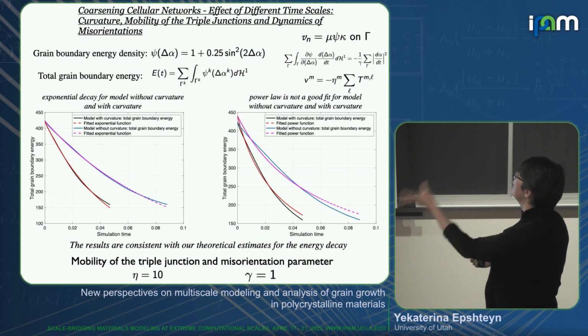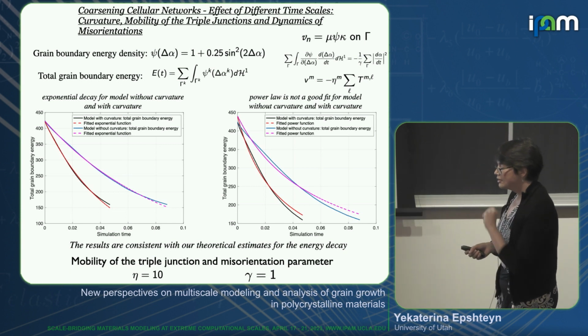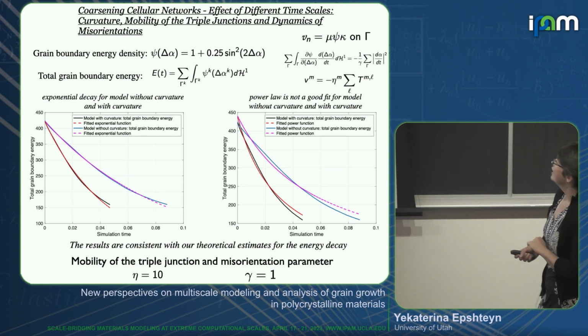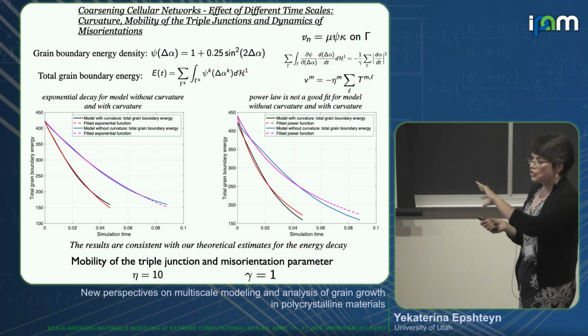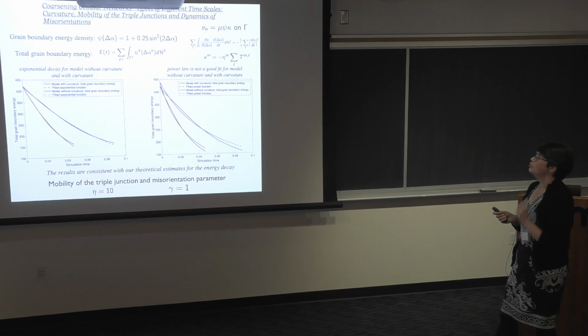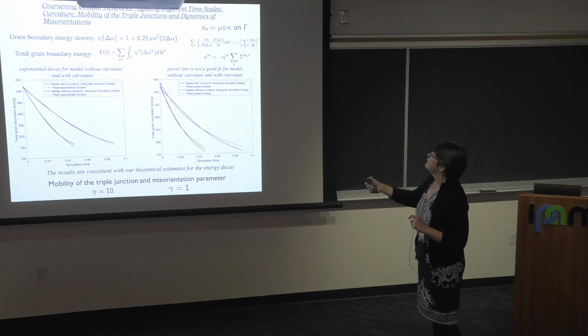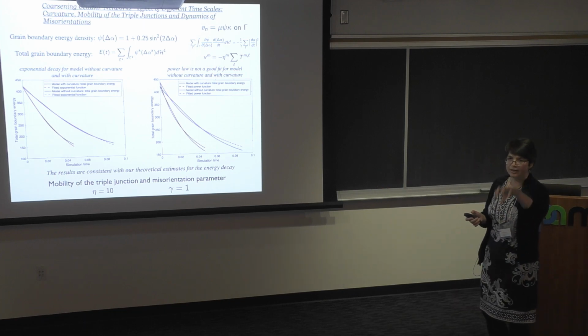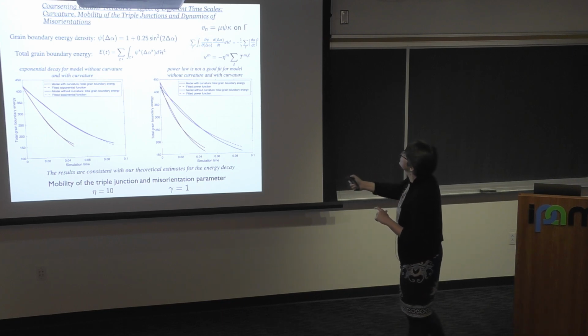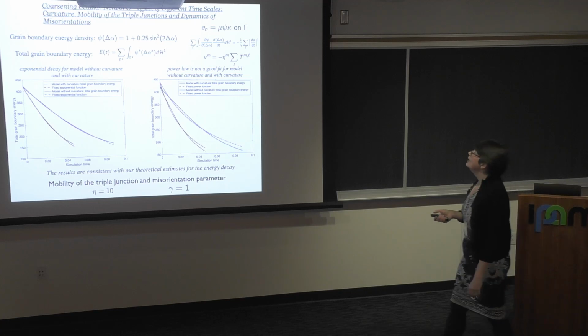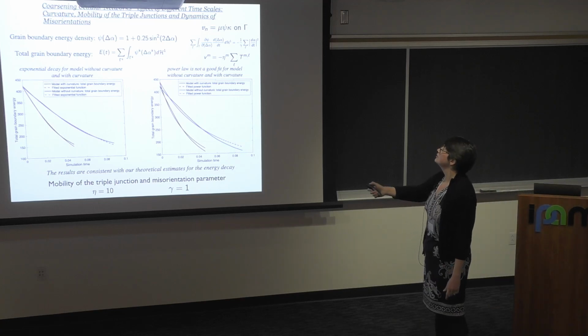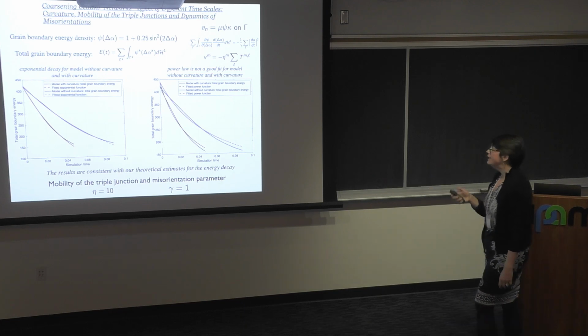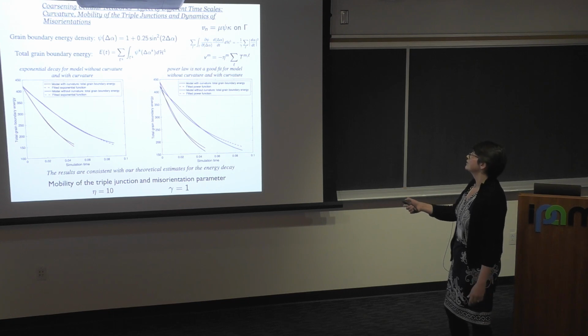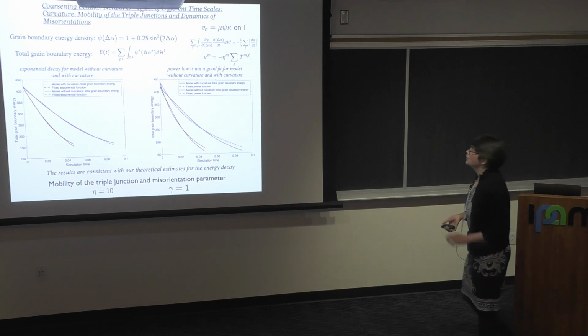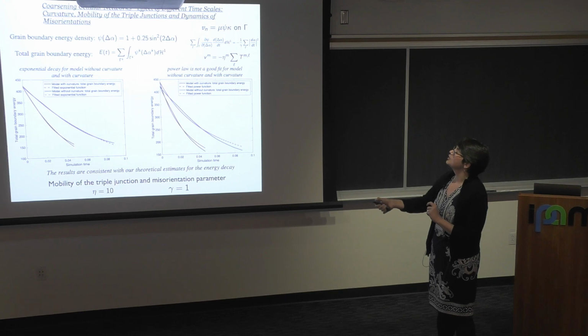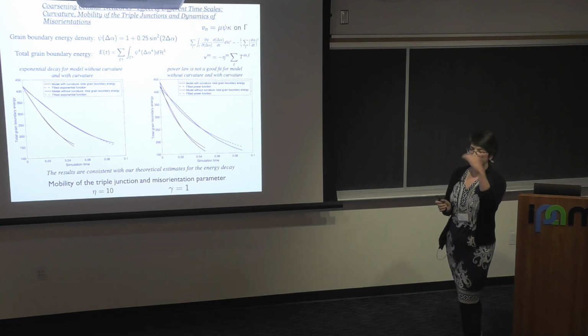Okay, but what I want to show, so I discussed that we have a reduced model where we relax dynamics of grain boundaries. We have a full model. So what we did numerically, we wanted to compare in some aspects the reduced model and the full model. Numerically, I will consider the full model that takes into account dynamics of grain boundaries, dynamics of orientations, and dynamics of triple junctions. And I will compare it with a reduced vertex model where we removed the curvature effect, and we only look at the dynamics of triple junctions and dynamics of misorientation or orientation. And what we did, we looked at the total grain boundary energy and how it decays with time.